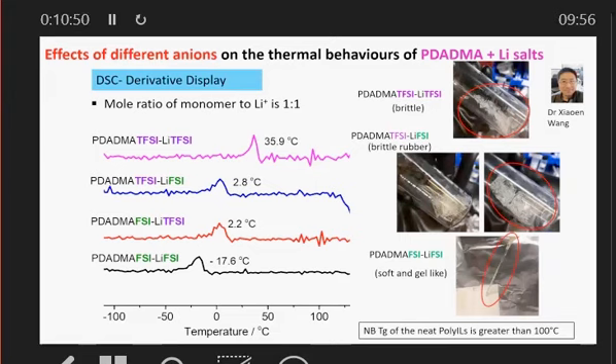So here we see that when we added 1 to 1, so 1 mer unit of the polymer to 1 LiTFSI salt component, we form a material that's actually quite brittle, not really a very nice material, but quite high Tg. So we kind of discarded that, and then we looked at what happened. We mixed the anions TFSI, FSI 1 to 1 again, and we see, independent of whether you start with a TFSI polymer or the FSI polymer, when you have 1 to 1 TFSI, FSI anions, you get a Tg of around 2 degrees. The material is softer, it's still quite brittle.